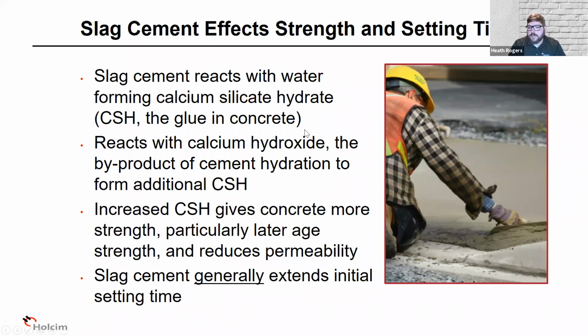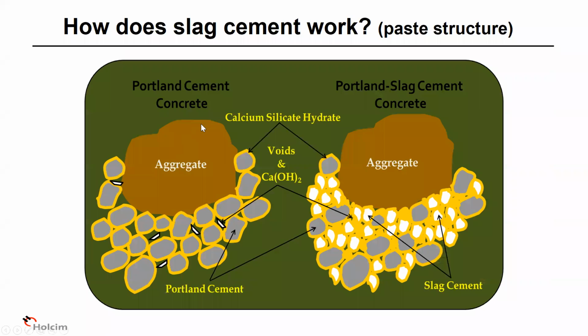Slag cement can then be used in concrete to replace some of the Portland cement in the mixture. So when you look at Portland cement in a really small detail, basically whenever water hits it, it grows fingers, and that's how it gains strength. It grows this calcium silicate hydrate, and all that interlocks with the aggregate and the other cement around it.